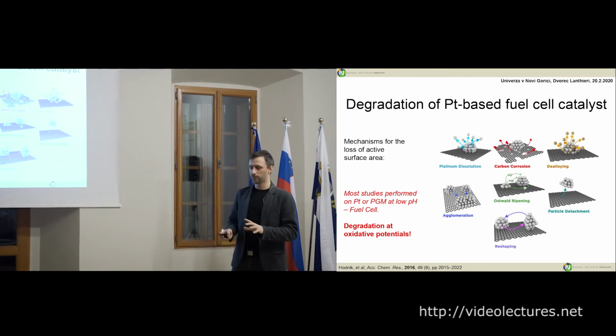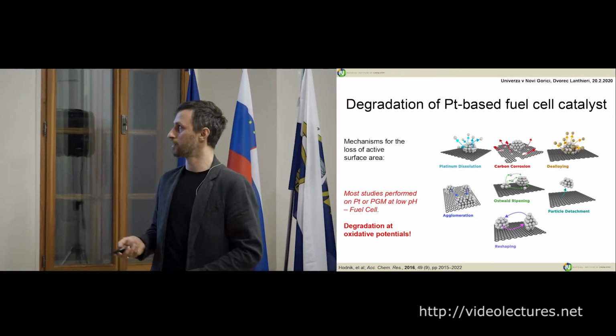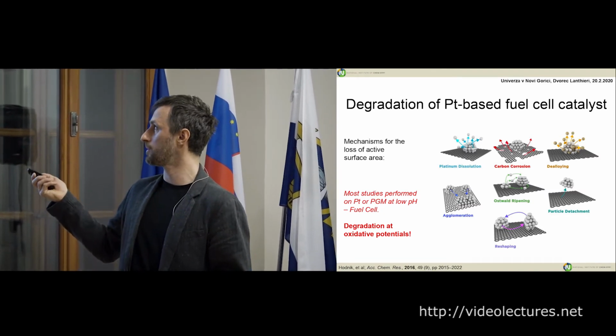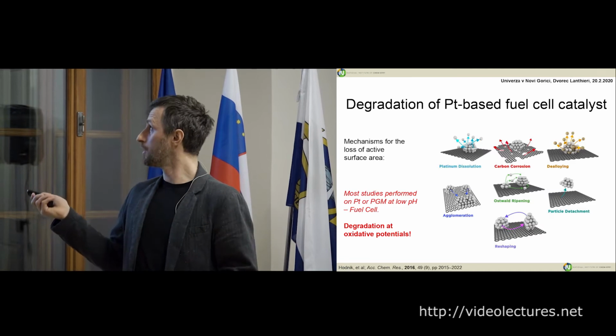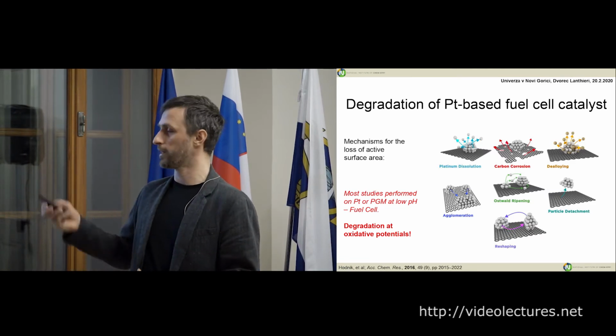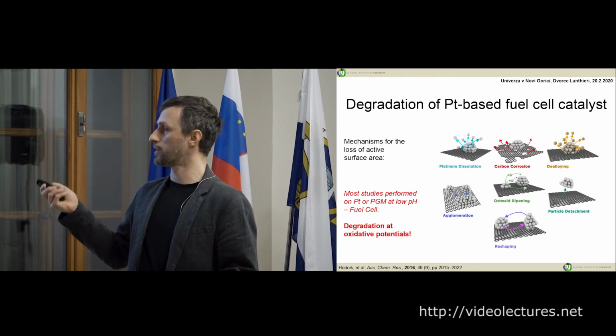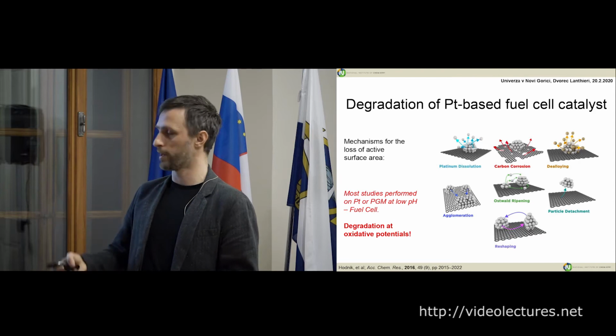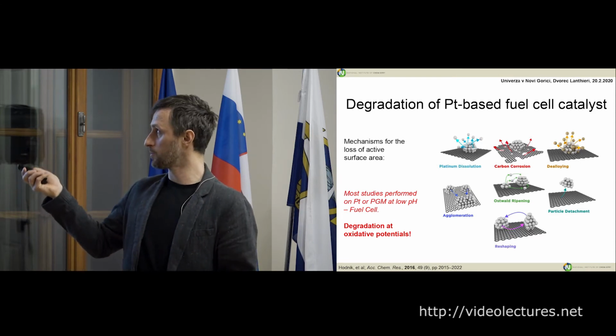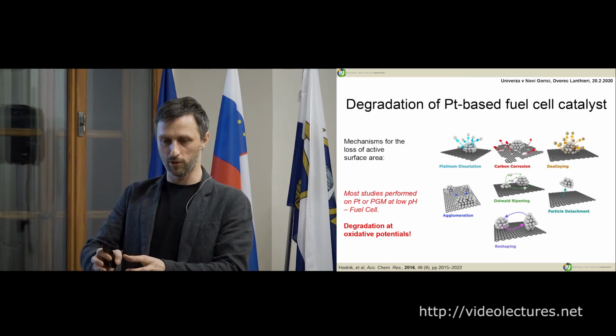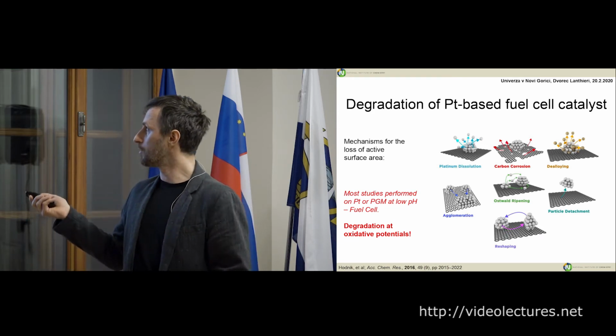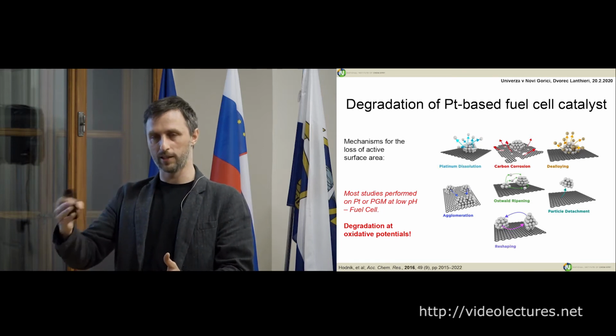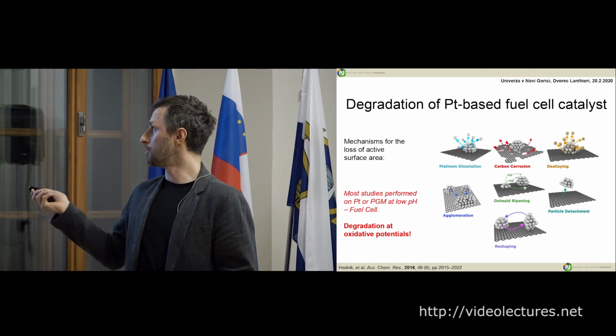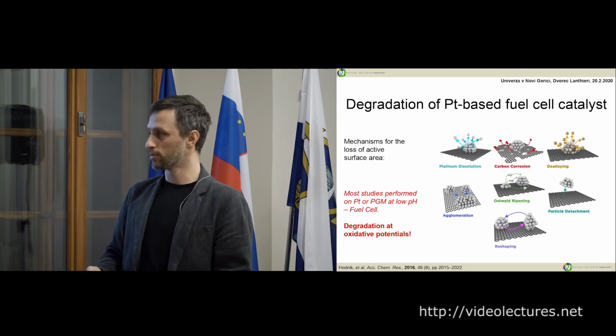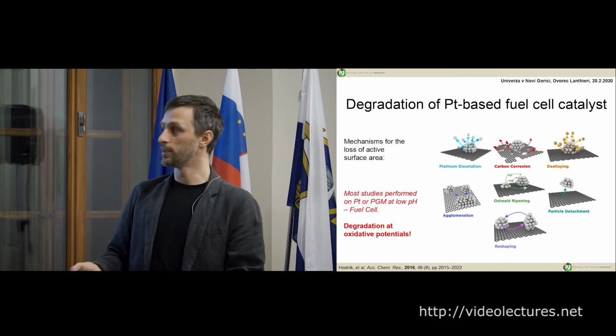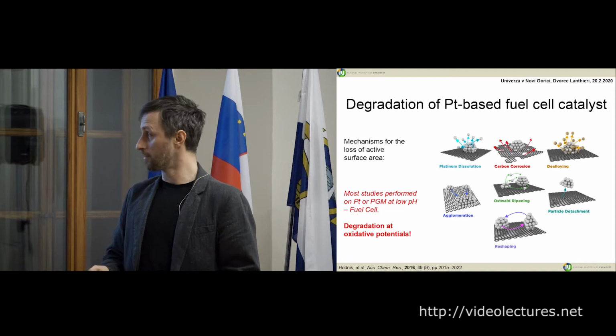If we try to understand this, we must first map out the different mechanisms that can occur. You can lose surface area by dissolving platinum, by corroding the support, and by, of course, dealloying, so removing of a second metal. This can be considered as primary mechanisms, and then these below are secondary because they result from the first ones. So you have agglomeration because you maybe corrode some support and particles coalesce. You have Ostwald ripening because you dissolve smaller particles and redeposit on the bigger ones. You detach particles because you probably have carbon corrosion. And then you can also reshape. So this all influences their structure.